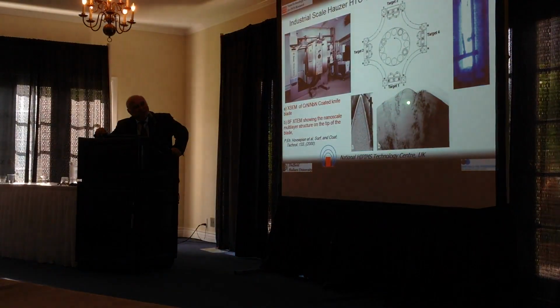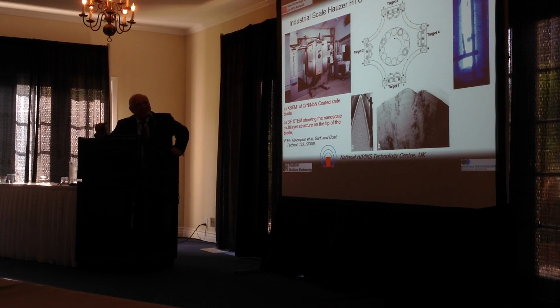In 2000, we were basically forced by industry to demonstrate that we can deposit with high precision these fine multilayer structures on 3-dimensional components. And this shows you a cross-section of a scalpel blade coated with a coating, and in TEM you can clearly see, I hope you can see them, I don't know, the light could be very different for you, but you can see the layer structure. So it was clear that we can put these coatings on a cutting tool, on a turbine blade, or whatever 3-dimensional component with very high accuracy.